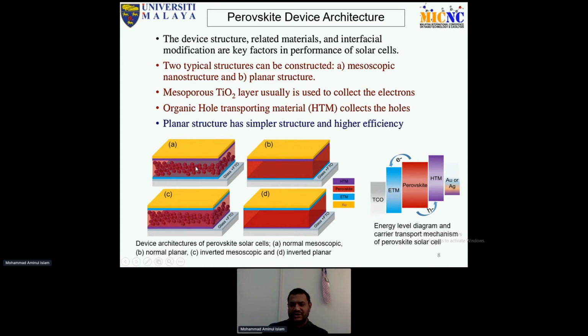But when going for research, these other structures come up, which we call the normal planar, and this is the inverted. The inverted means you replace the ETL, electron transport layer, and the hole transport layer, changing the position. So when changing the position, we call it inverted. And in the case of mesoporous titanium oxide, we have a solid layer. No need to have any mesoporous structure. So we have a solid N-type layer, and then give directly to the perovskite layer. This is the perovskite layer, and then the hole transport layer and others.